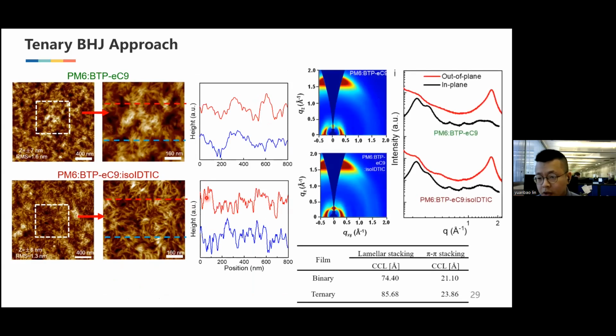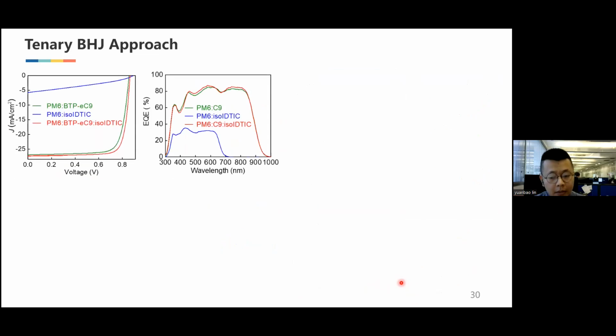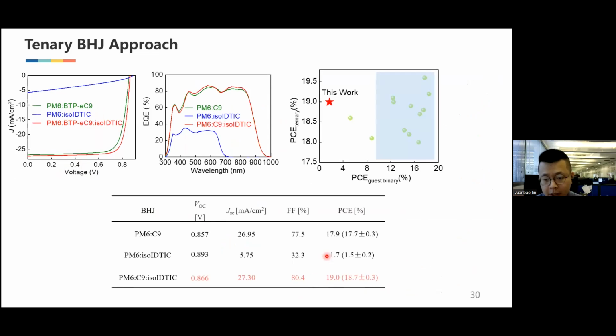We also got some pi-pi stacking order from GIWAXS data. The ternary has higher crystallinity in the pi-pi stacking, and also a slight increase in the lamellar stacking. But because the absorption of iso-IDTIC is very close to PM6, in the binary PM6:iso-IDTIC we only got 1.7% PCE. But if we add it into PM6:BTP-eC9, we can enhance it to 19.0%, which is better, because the fibrous structure can enhance charge transport and also slightly increase the VOC.